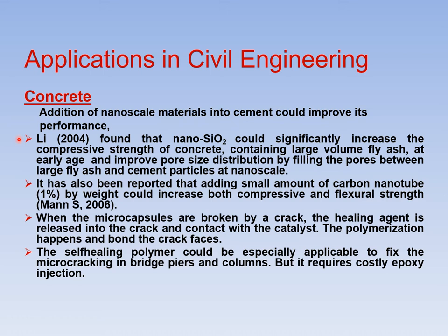So Li 2004 found that nano SiO2 could significantly increase the compressive strength of concrete containing large volume fly ash at early age and improve pore size distribution by filling the pores between large fly ash and cement particles at nanoscale.